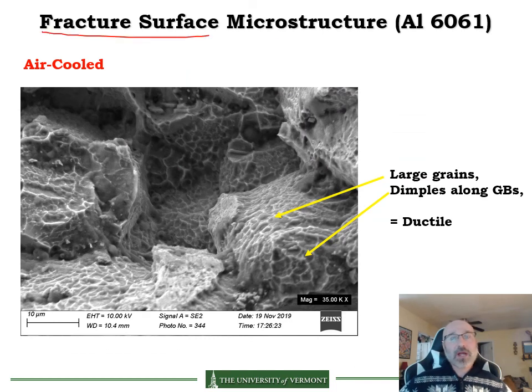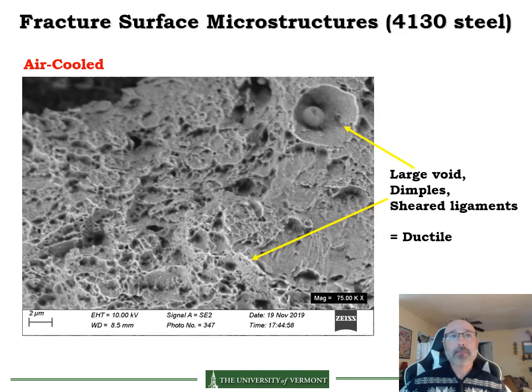As we continue looking at the fracture surface of the microstructure, this one, in this particular case, is 6061 aluminum. It's air cooled, but we can still see for this ductile material, in this image, you're seeing these long grains and the dimpling within the image. That's something that we're going to see for any of these ductile types of materials when we look at them under a scanning electron microscope. Now if we continue on, we're talking about a 4130 steel that's ductile. This is what it's going to look like. You're going to have these larger voids, the dimples you're still going to see there, and you're going to have some sheared ligaments. That's what an air-cooled 4130 steel looks like when you're looking at it through a scanning electron microscope.